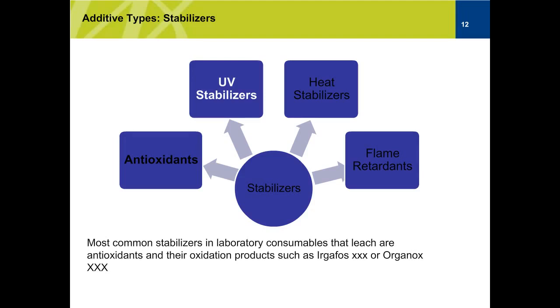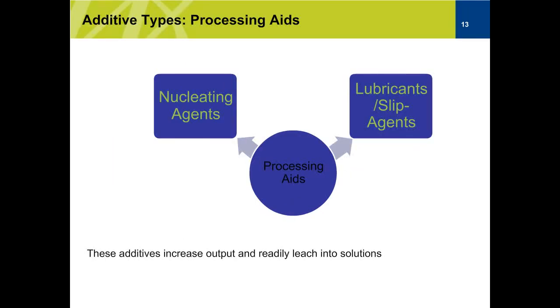So antioxidants really perform by eliminating the oxidation during and after processing when the material is exposed to any energy source. UV stabilizer is the same thing. They protect the materials from UV radiation exposure over an extended period of time. And usually, if you do an extractable study, these would be Irgafos XXX, meaning there are a couple different numbers, 68 or 168 or what have you. And Irganox is another antioxidant that is readily seen, that readily leaches from the labware.